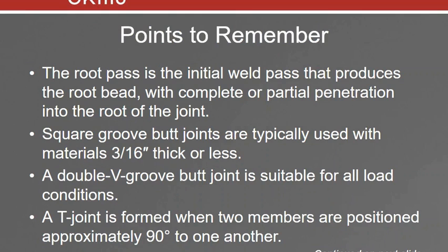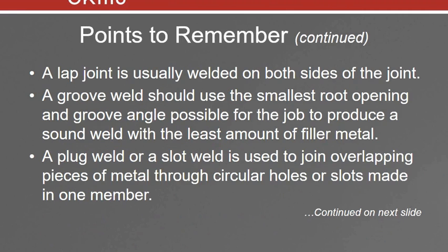A couple of things to remember. The root pass is the initial weld pass, okay, with complete or partial penetration into the root of the joint. Remember, the more penetration you get, the better off you're going to be. Square groove butt joints are typically used with materials 3/16 or less. If it's 1/4 inch thick or more, put a bevel on it. Double V groove is suitable for all load conditions. T-joints are formed when the members are positioned at 90 degrees to one another. A lap joint's usually welded on both sides, but can be welded on one side depending on what you're doing.